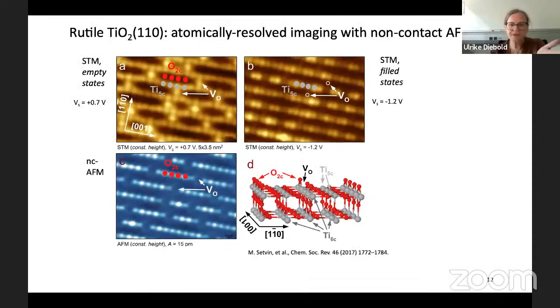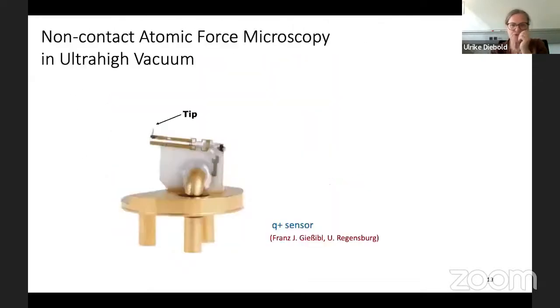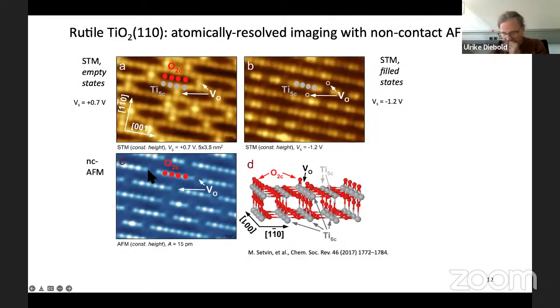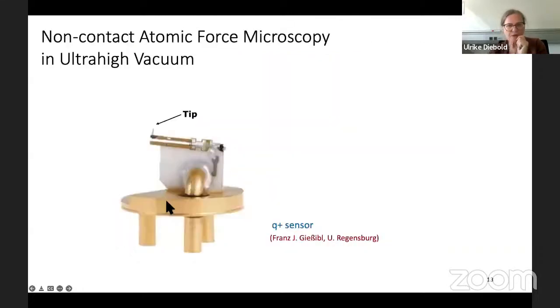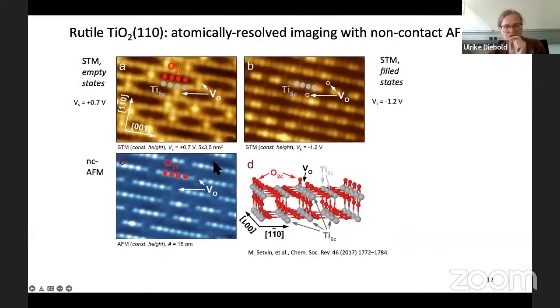So we can look at these things. We can look at these surfaces with atomic resolution, and in fact, I should maybe point out, so I get a little bit more into the details, this is actually a non-contact AFM image where we measure the frequency shift of this tuning fork. Here's an STM tip, so a sharp needle, this is about 10 millimeters or so in size here. We bring this in front of the surface and we measure the resonance frequency when the tip of this non-contact AFM interacts with our surface. So what's shown here is a change of the resonance frequency as we scan across the surface of this tuning fork.